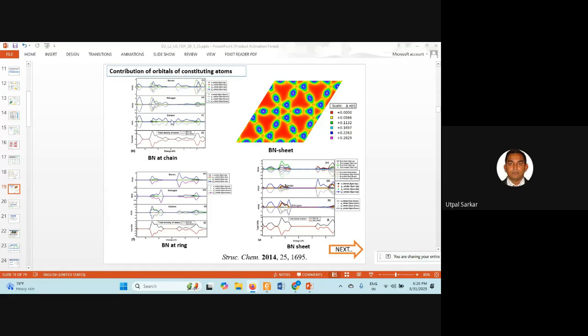So for carbon atoms, when it is BN at chain site, you have some band gap, and there is no density of states here. Now here the carbon atom is also in the valence band. In the valence band, carbon atom is contributing, nitrogen atom is contributing, but the nitrogen contribution in the valence band is more prominent than in the conduction band. So these features tell us that whatever electrons are available are basically from the nitrogens. Similarly for the other structure also, you see that the boron's contribution is basically in the conduction band, and nitrogen is basically in the valence band.